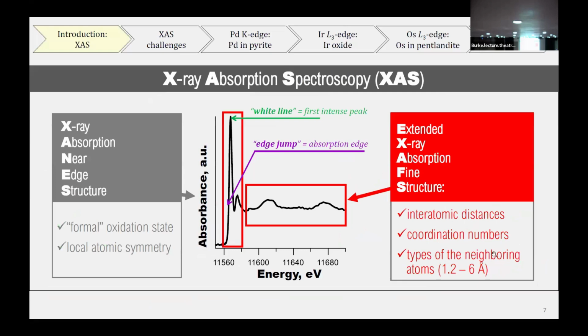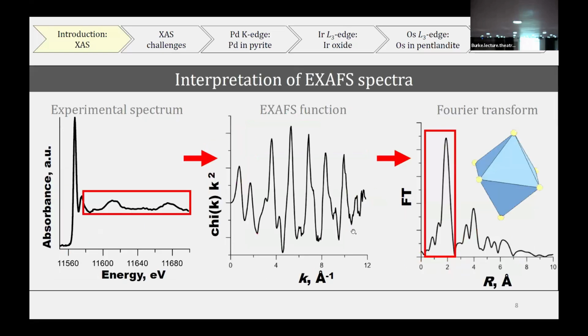Yeah, if we continue recording, we will record the extended fine structure. This region of the XAS spectrum tells us everything about neighbors, about interatomic distances, coordination numbers, and types of the neighboring atoms. Just very briefly, if we recorded the full XAS, we can extract the EXAFS function, and performing a Fourier transform, we will be able to see the local atomic environment of the absorbing atom, which will normally be at 0. And then the x-axis would correspond to the interatomic distance between the absorbing atom and the coordination shells, where every contribution would be a coordination shell. First one, second, and so on. So here it's 6 sulfur atoms, it's PdS2.